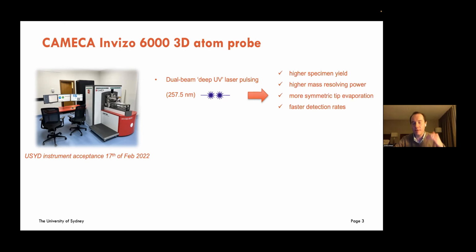And this is basically enabling a significantly higher specimen yield, a higher mass resolving power in general, and this dual beam capability, where the laser beam is split and illuminates the specimen from either side, allows for a more symmetric tip evaporation. That has some implications for simplifying reconstruction protocols and also enabling faster detection rates, so we can crank up that detection rate a little bit more with this new laser technology.